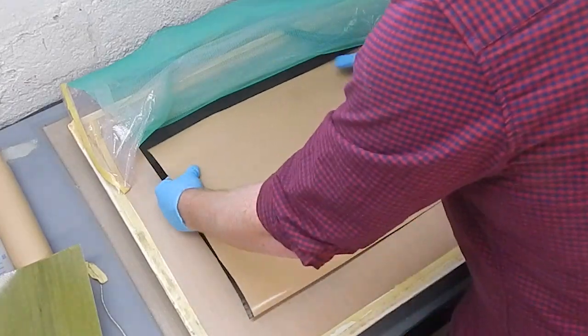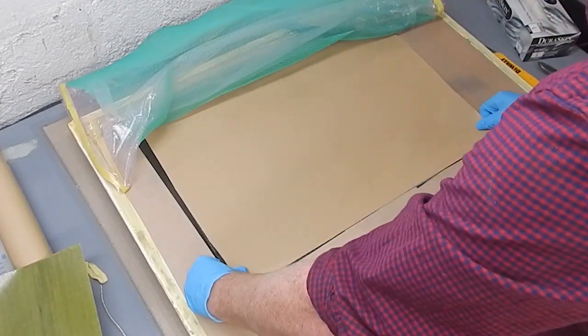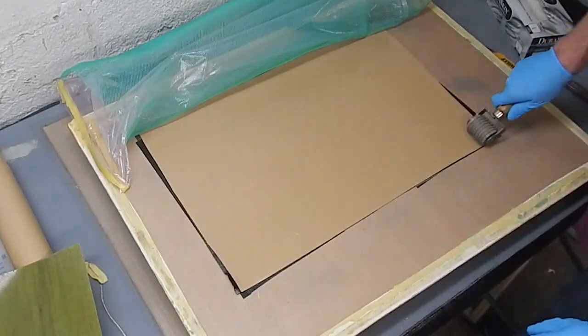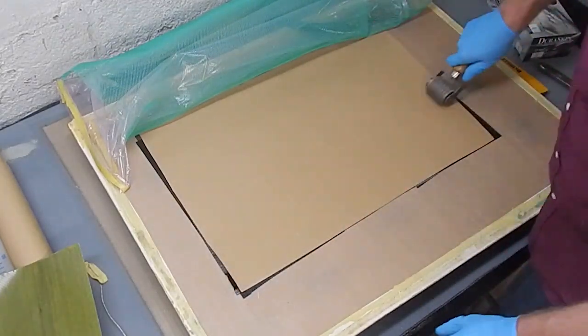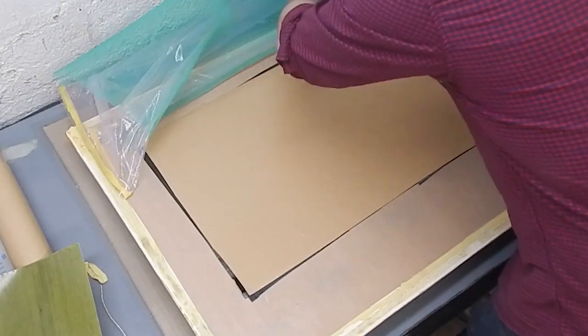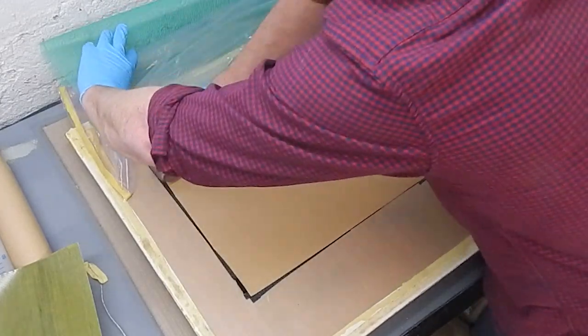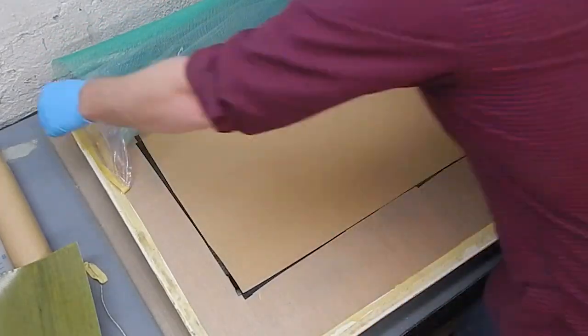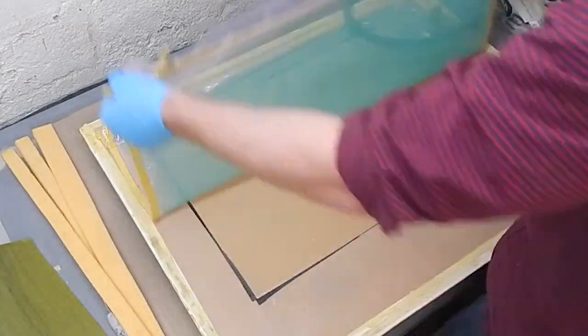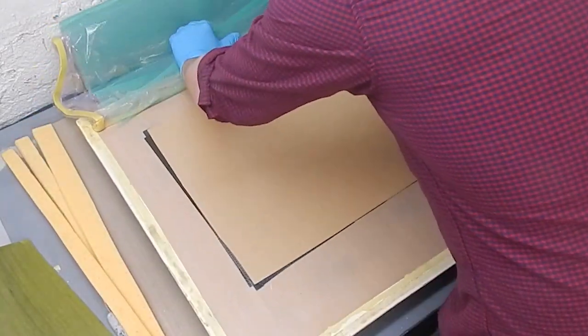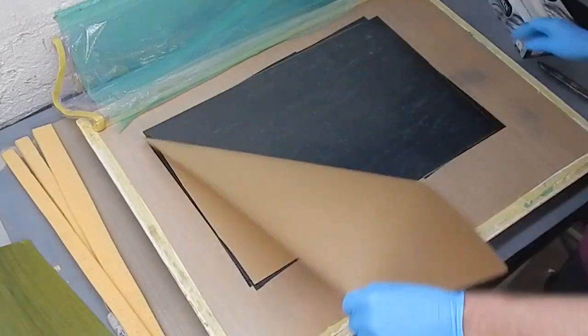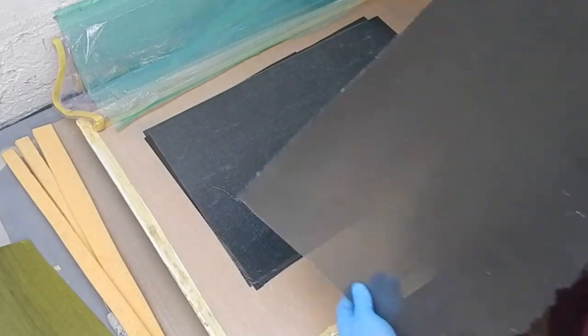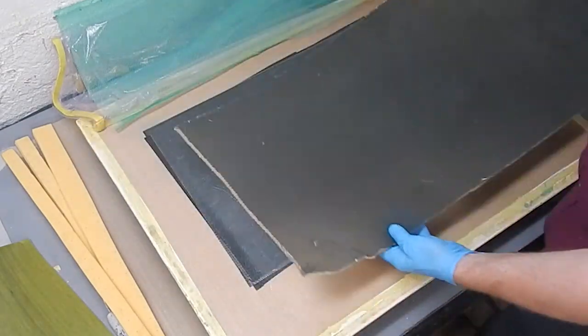And this is the final ply of that skin with the glue film co-applied. I'll stick that down and leave the paper backer on the glue film because it's super sticky and it will get all over the bag and everything else. But just using the spiky roller to perforate that, that was the world's quickest debulk. You can see it's nice and smooth, not much air in there.